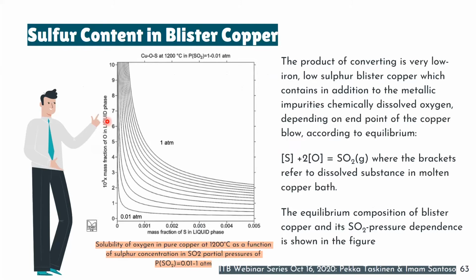And then because we introduce oxygen to remove sulfur, of course there will be some amount of oxygen dissolved in the blister copper, and this oxygen will be in equilibrium with sulfur dissolved in the copper also, and in equilibrium with sulfur dioxide. And we can see here the relation. If we want to remove more sulfur, it means we need more oxygen. It means more oxygen will be dissolved in the copper, and therefore, when the sulfur is reduced a lot, to a very low concentration, at the same time, the oxygen concentration will be high. This is the example. The concentration of the sulfur and the oxygen in relation with oxygen pressure at different total pressure.